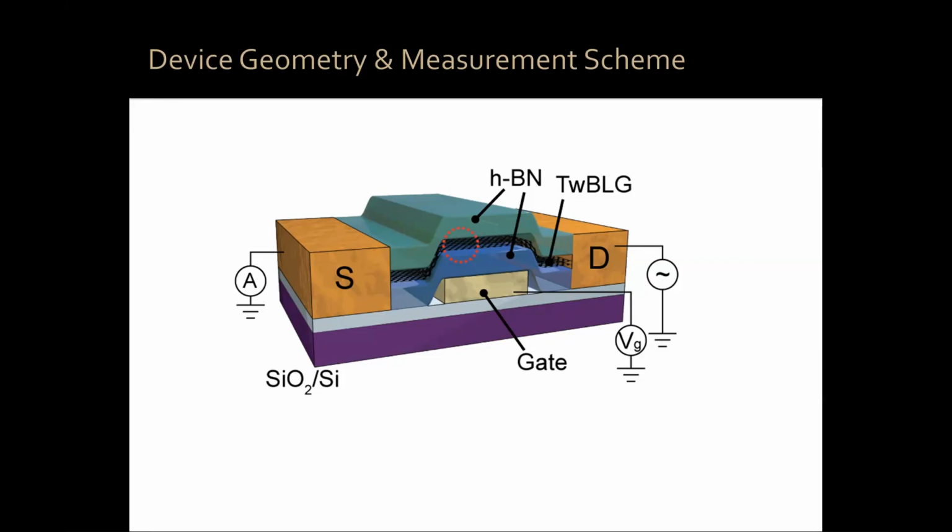Fabricate that device, the bottom gate and so on, you do it in the clean room, and then you just bring what you have made before and then just stack them. That's right. We have what we call the stack, which is the hBN twisted bilayer graphene hBN structure, and that thing is on a substrate, and then we go to the clean room and we fabricate. The bottom gate can be a metallic gate or it can be a graphitic gate. So if it is a graphitic gate, you have to do extra stacking. We often have a top gate, which can be a metallic gate or a graphitic gate. If it is a dual gate graphite, then you have to have graphene, hBN, twisted bilayer graphene, hBN, graphite. So it's a multi-stack process.